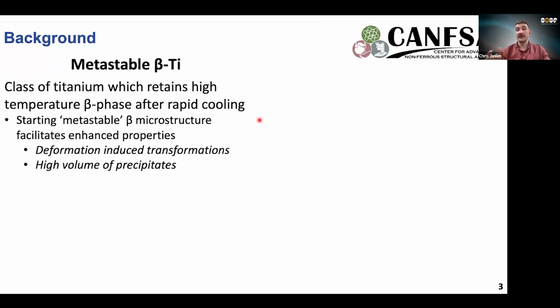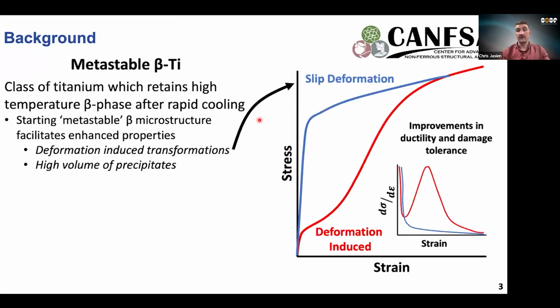This starting metastability can facilitate enhanced mechanical properties, one being what are called deformation-induced transformations. For instance, in a typical material, you'll see a stress-strain relationship where as you strain, you hit some yield point, and then you level off and fracture. However, with deformation-induced phase transformations, you reach a certain point which is enough to trigger this transformation, and you get a significant increase in your work hardening. Not strain hardening, work hardening. And so you get improvements in ductility and damage tolerance over a typical relationship.